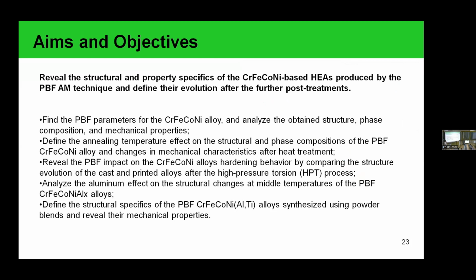So the aim of our work is to investigate the structural and mechanical properties of this 4-component system produced with the powder bed fusion technique, and try to improve these characteristics using in situ alloying with aluminum and titanium. To achieve this purpose, in the first stage, we found the required printing parameters for our 4-component system, analyzed the structure, and also analyzed the further post-treatments, how they affect the structure and mechanical behavior of our materials.